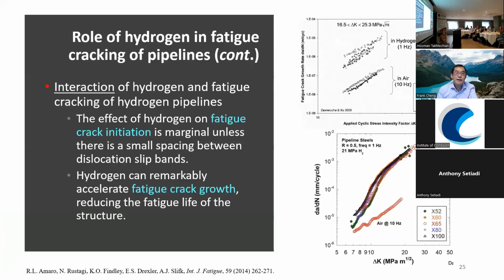At the same time, if hydrogen goes into the steel, it usually can speed up fatigue crack growth. So that's why, under hydrogen and fatigue, they can make the pipeline fail quickly, because hydrogen can speed up the fatigue cracking process.